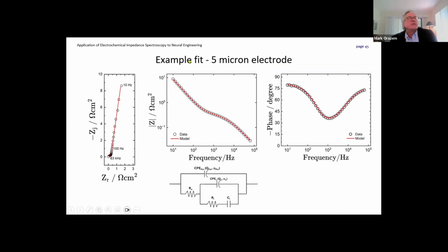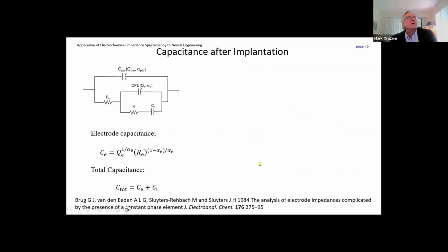So this is an example of the fit to the data that I showed you in that accuracy contour plot. And you can see that it is really quite a nice fit to the data. And I'm focusing here on the capacitance after implantation. And so we are going to take from this electrode, from the flat surface, we're using the Brugg formula to estimate a value for the capacitance.